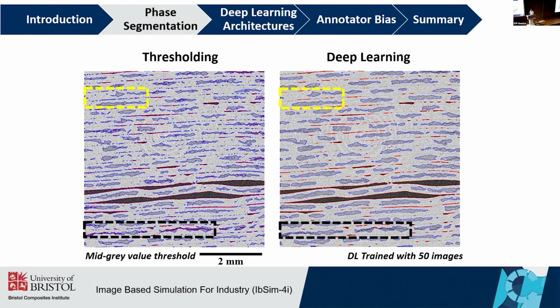So these are the main visual results comparing thresholding to deep learning. What we can see at first view is that thresholding is pretty noisy, especially in the segmentation of dry areas, which are in blue. Of course, we can improve the results by implementing some post-processing, removing some noise, etc. But there are some things that cannot be achieved using thresholding.